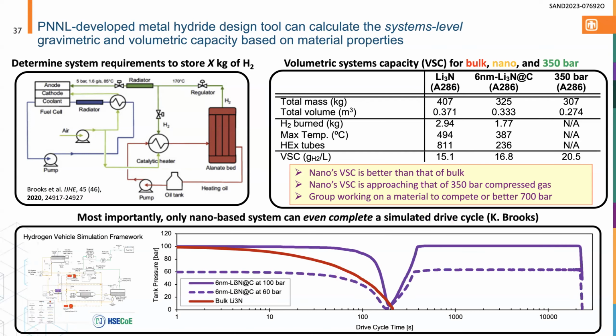So the nanoscale material actually does better than the bulk, despite it having a significantly lower gravimetric material capacity. And this mainly comes from its increased thermal conductivity and its decreased delta H. So you get lots of really interesting insights on that. And while this material isn't able to beat 350 bar, the Sandia experimental team, I'll just mention, is working on a material that will compete with or be better than 700 bar in these vehicular applications. So that's a pretty exciting result.